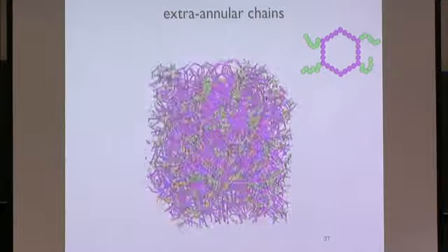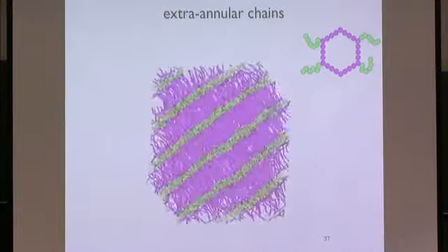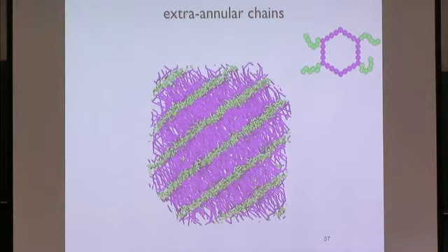You see, again, as we start quenching, we start seeing the appearance of a very interesting lamellar structure. If we take a look at it carefully, what happens is that the rings themselves have segregated from the chains in such a way, and the reason for that is that if we look carefully at the rings, they actually interpenetrate one to each other. So therefore, by interpenetrating, they're decreasing basically their excluded volumes, and therefore they find a more suitable phase.